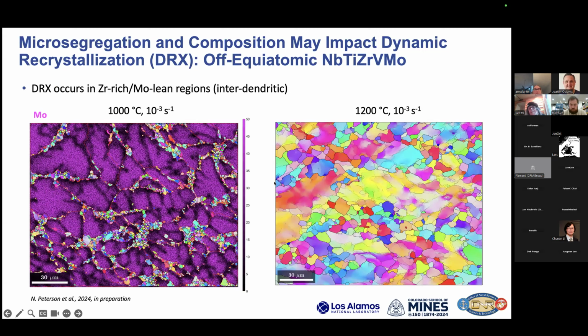And so here you're actually looking at a molybdenum map of a multi-principal element alloy. And we can see in the dendritic regions, we have higher molybdenum content. In this case, it turned out we had higher zirconium content in the interdendritic regions. Then in this case, we actually went ahead and did thermomechanical processing. So here we're doing hot deformation at 1000 C at a quasi-static strain rate. And what you see is we start kicking off dynamic recrystallization or DRX in those interdendritic regimes.